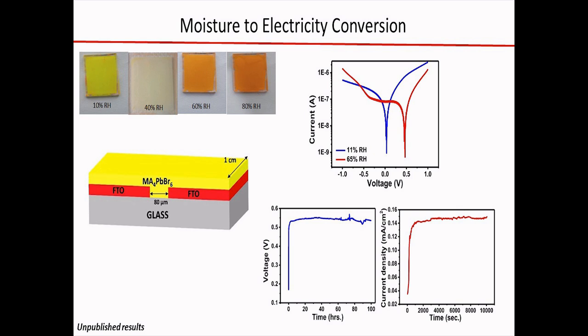Interestingly, when we measured the IV curve at two different humidities, this is all done in the dark—there is no light, no sunlight involved. When we measured them in the dark at two different humidities, you can see that there is actually an open circuit potential. The minimum of this current is not observed at 0 volts, but at a certain voltage.